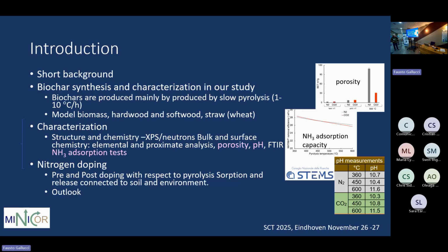What is interesting now, this presentation is focused on nitrogen doping. We have two types of doping. One is pre-doping, that is, you dope the biomass before you pyrolyze. The other is that you use pyrolyzed biochar and then dope it and characterize it. This is interesting because in the first case, it comes into play with the pyrolysis chemistry, so it will play a role in the chemistry and give a final biochar product which is different than you would expect in the second case where you dope afterwards. That can be interesting for different applications, in particular for soil and environment applications in our project.